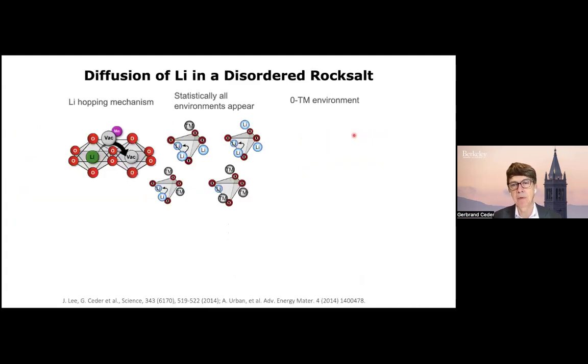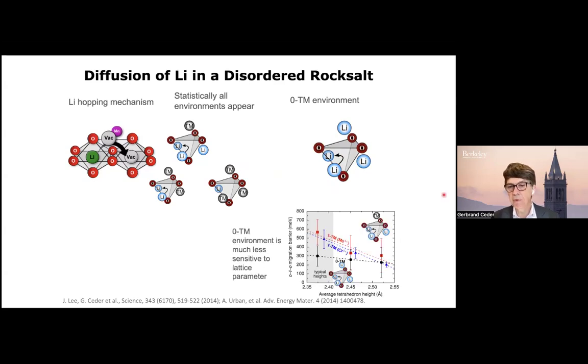So that's how we got to disordered rock salts: if you disorder the cations in the rock salt crystal structure, you statistically create all kinds of environments around this tetrahedral site. And the one that's really intriguing is this one. It's the one where there's only lithium, or as it's now referred to, a zero transition metal environment. Because what you see here is that if you actually start to extract lithium and make some vacancies, then this lithium, when it's in the tetrahedral site in the activated state, will have very little electrostatic repulsion, which means it will not suffer a lot from this slab space contraction. And that's what you see in calculations.